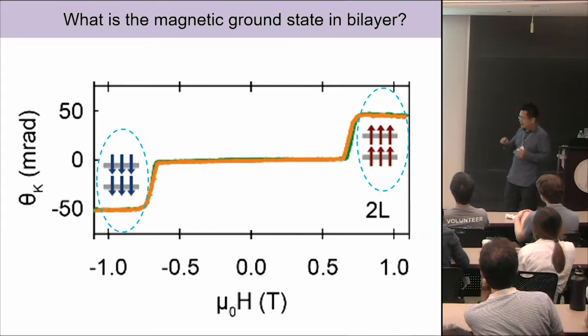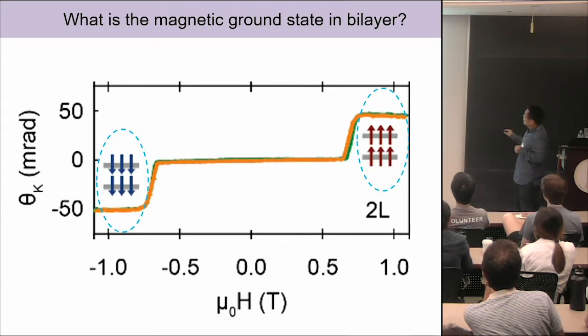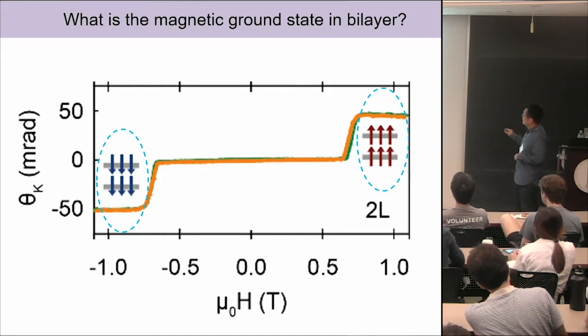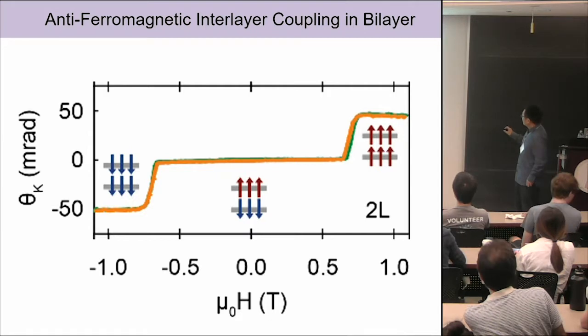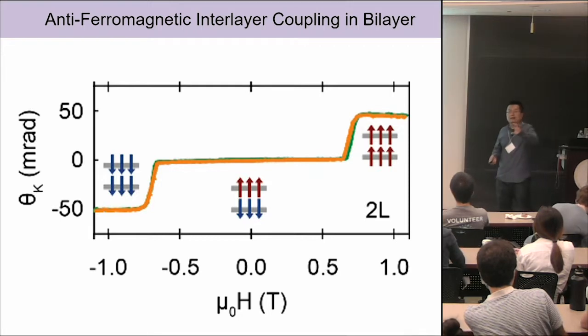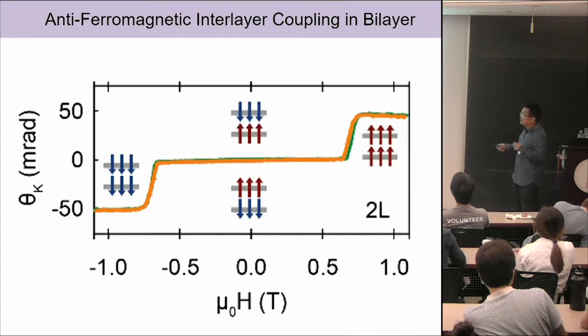It's anti-ferromagnetic. What that means is, first of all, when the magnetic field is large, you can align all the spins in one direction. So we get magnetization, and then we see large Kerr rotation signals. However, at small magnetic field, each individual monolayer is still ferromagnetic, but the interlayer coupling becomes anti-ferromagnetic. So the magnetization is compensated, and therefore there's no net magnetization. So there are two ground states, and they are time reversal of each other.